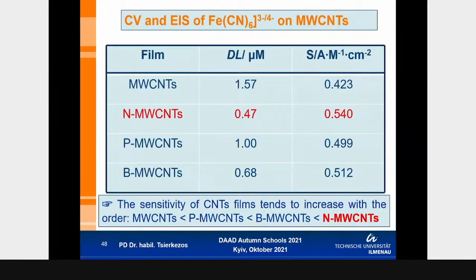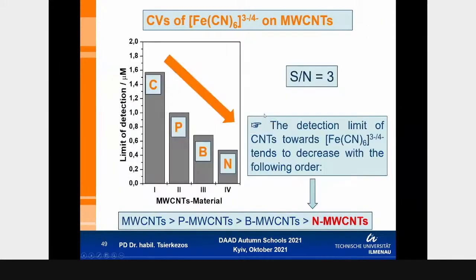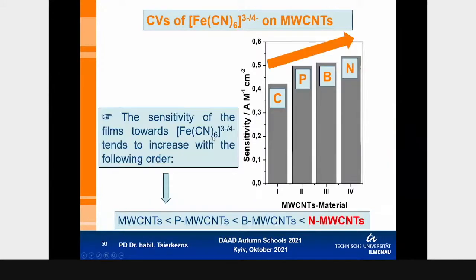And once more here, a table which shows the electrochemical parameters calculated for the redox system. DL is the limit of detection, and sensitivity is the sensitivity of the electrode against the redox system. You can see that the lower detection limit and the greater sensitivity have been observed for the nitrogen-doped carbon nanotubes. Once more in a histogram, you can see that the limit of detection tends to decrease from pristine to nitrogen, and consequently the sensitivity increases from the pristine to the nitrogen, which means that the doping with nitrogen leads to better electrocatalytic activity.